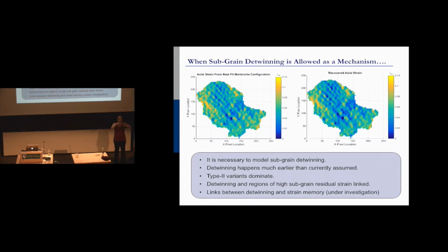When you take this stent and you squeeze it, and you're in the middle of that stress plateau, you're actually causing detwinning, and this detwinning is linked very strongly to residual damage. So you're getting this very early. It causes residual damage in your stent. It hurts your stent. We need to consider it, and we need to figure out a way to knock it out so it happens later. We need to figure out a way so that when we squish the stent, we don't get detwinning, we don't get residual damage, and it'll just come right back.